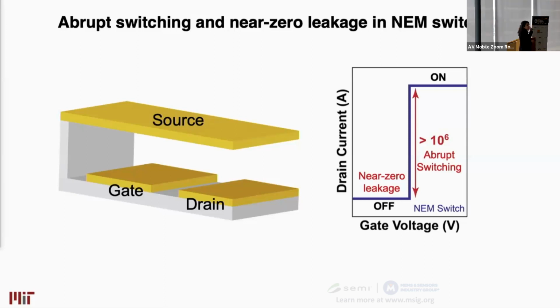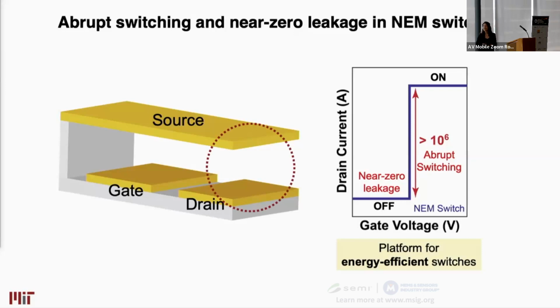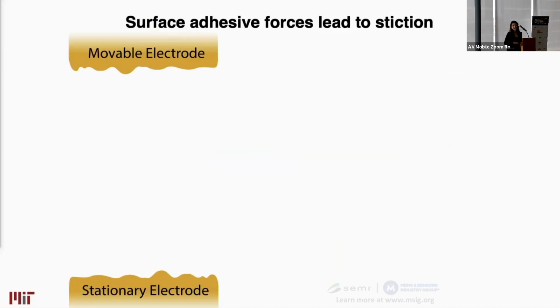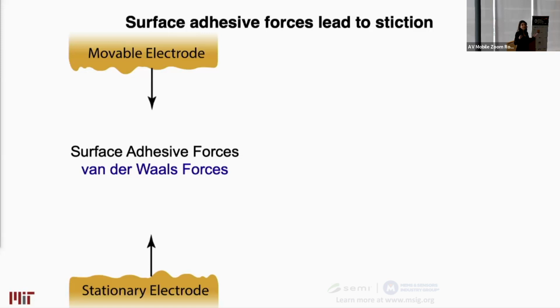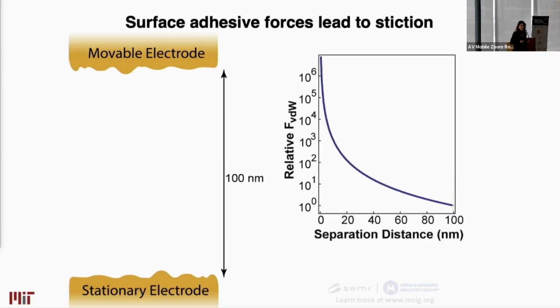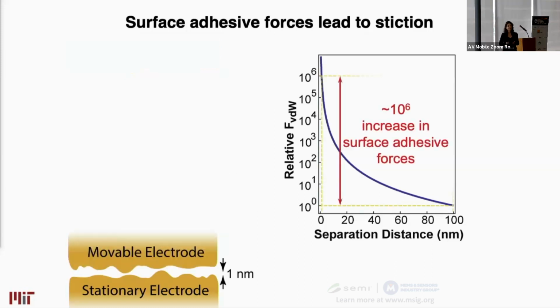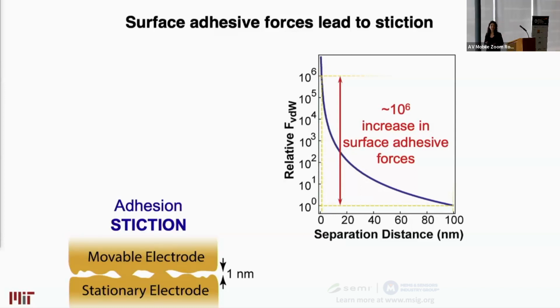But of course, what I'm drawing here for you is just a schematic, an ideal case. And before we can actually reach this ideal situation, there are quite a lot of challenges that have to be overcome. And I'll focus on those by zooming into the switching gap. So in an electromechanical device, there's a movable electrode, surfaces that are nanometer distances away from each other. They experience large surface adhesive forces. And these forces scale with the switching gap dimension. So take your switching gap, going from a gap of 100 nanometers in size to 1 nanometer. Just in van der Waals forces alone, you're going to get at least 6 orders of magnitude increase in surface adhesive forces. And that causes the surfaces to experience large surface adhesion, leading to stiction in these devices.